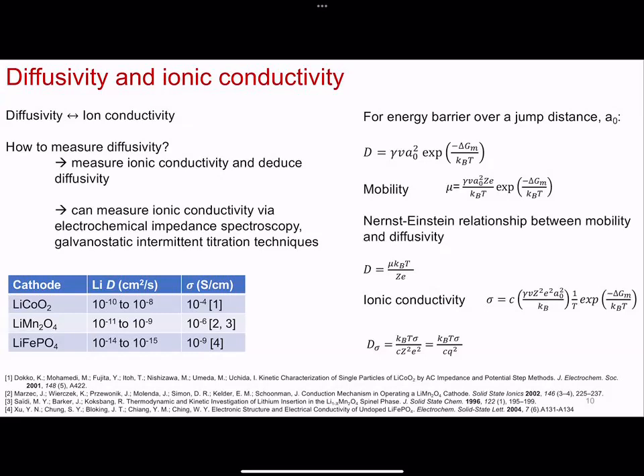So the diffusivity will change as a function of the crystal structure and the direction. If it's a single crystal and you can control the crystallographic direction that the ions are moving by applying the field a certain way, then you can get diffusivity. So then you can also understand what the different activation energies are for each particular regime, right? So you're going to get different slopes. And if there's a phase transformation, there's going to be an abrupt change in the Arrhenius plot, right? So you can see all of that and map it out as a function of temperature in your Arrhenius plot. So it's quite powerful to be able to relate